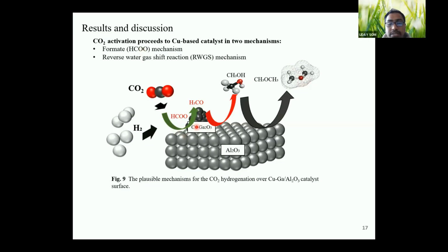So the first intermediate is the formate species, which involves the lattice oxygen atom on the copper oxide catalyst. The CHO formyl is hydrogenated to form the methoxy. The formation of the methoxy species is the kinetically relevant aspect for methanol synthesis on copper-based catalyst.